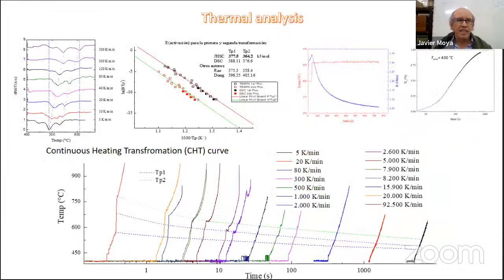Well, from the derivative of the electrical resistance with time or temperature, we can obtain a graph similar to that of the DSC test and get the activation energy in a wide range of heating rates. In this case, up to near 100,000 Kelvin per minute.